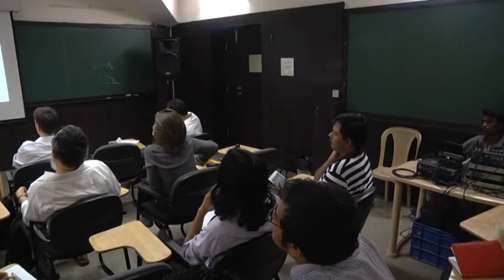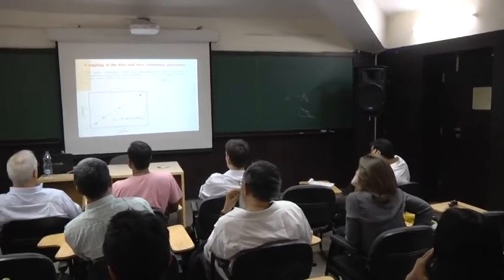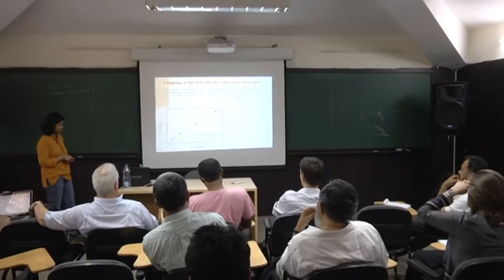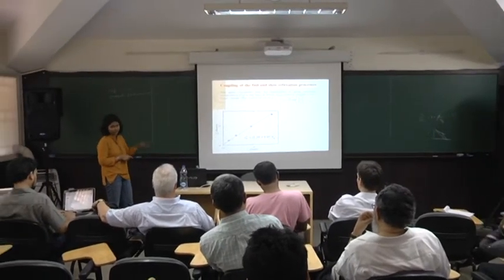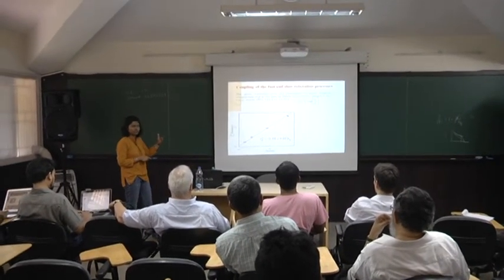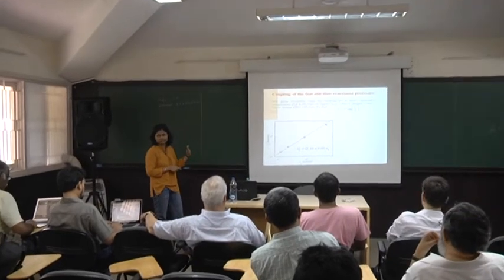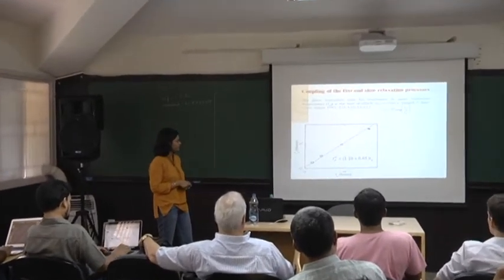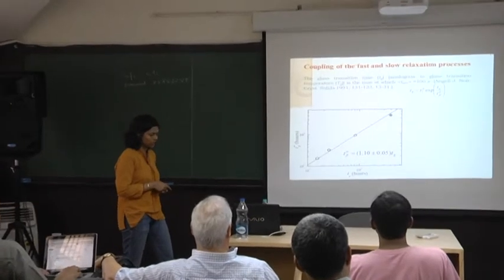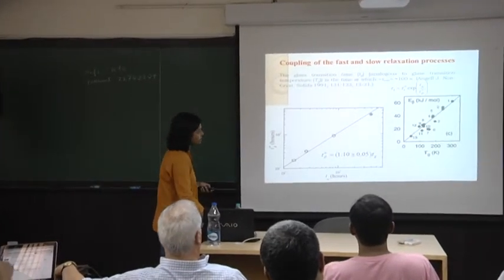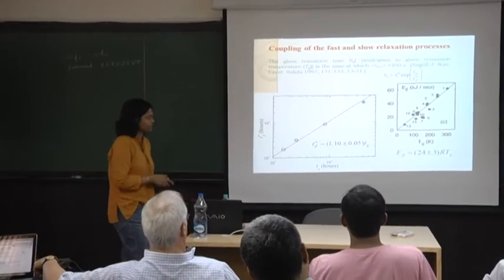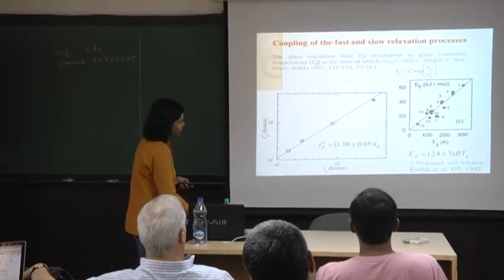And again, you can obviously collapse all the data. We also find, so remember these two time scales that we have, the Vogel time as well as this time scale that quantifies the beta relaxation process and the glass transition temperature, which we used as 100. So this is the age of the system at which the relaxation time reaches 100 seconds. You can see that these two time scales are very well correlated, which is again something that people have seen in other fragile liquids.